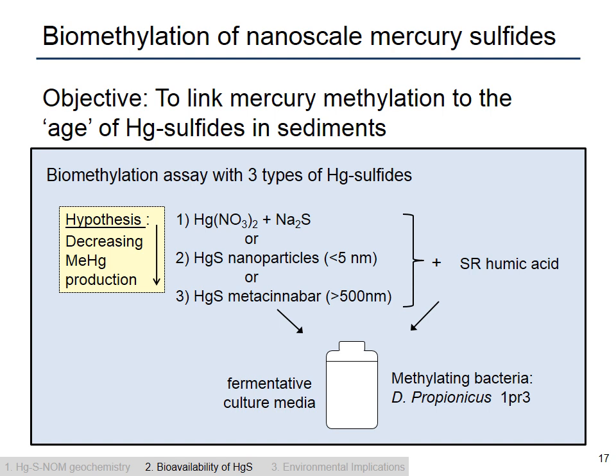So here the objective was to link mercury methylation potential or bioavailability to the age of mercury sulfides in sediments. And what I mean by age is that we're comparing dissolved mercury versus nanoparticles versus microscale particles. And so the way we did this experiment was that we cultured methylating bacteria, a sulfate-reducing bacteria that was actually grown fermentatively, and we exposed it to one of these three forms of mercury, dissolved, nanoparticulate, or microcrystalline metacinnabar, all at the same mercury concentration. And we were hypothesizing that the production of methylmercury will decrease as you go from the top to the bottom, as you go to longer aging states of mercuric sulfides.